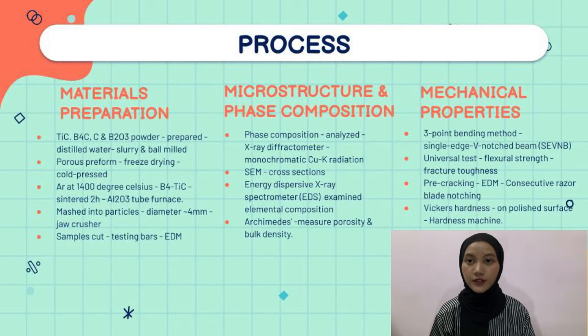In flowing argon at 1400 degrees Celsius, the porous B4C-TiC mixture was eventually sintered for 2 hours in an Al2O3 tube furnace. Secondly, the microstructure and phase composition.